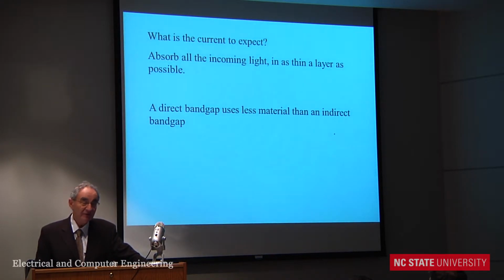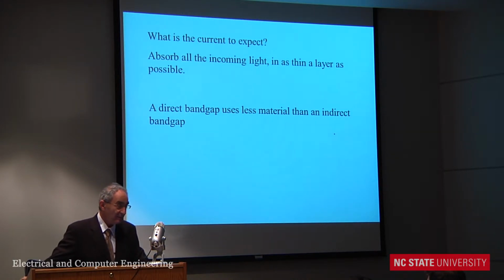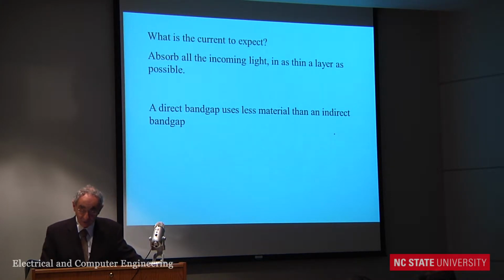And so you say, well, let me use a direct band gap instead of an indirect band gap, because I'll end up using less material. Now let's say we're talking, as I am here, about gallium arsenide. You say, oh my God, it's a direct band gap, but it's a more expensive material. But wait a minute, it absorbs hundreds of times more light. And it's 10 times more expensive than silicon, but I can use hundreds of times less material. So if you ask me, I will answer that the more expensive material is actually cheaper, because it's a direct band gap, you need much less material. And so that's one aspect of absorbing the light: you want to have a strong absorber, because then you won't need very much of it. And by the way, these films are about 1 micron thick.